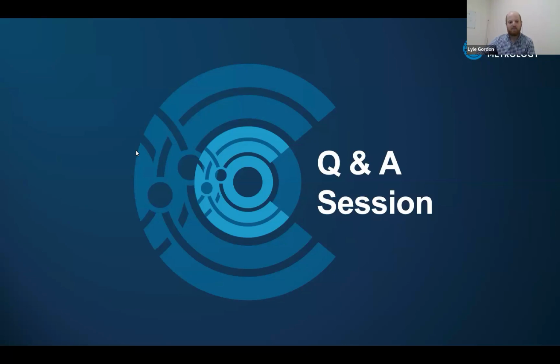Thanks. All right, we'll go on to another question. You mentioned in the talk that mostly the primary ion beam was bismuth. Are there advantages of using different primary ion beams? For organic samples, when you are interested in measuring larger ions, it's better to use a larger primary beam. So argon cluster is usually used for these cases. In the bismuth primary gun, we also have the option to modulate it between single bismuth ion or triple ion to improve the resolution for higher masses.